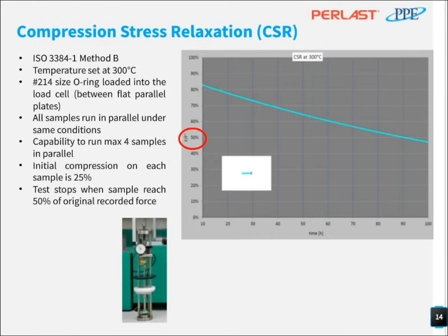And then it starts measuring the retention force, and then we put the whole system into the constant temperature oven, which is in this case 300 degrees C. We can use 4 cells at the same time in the oven, which gives us opportunity to test multiple materials at the same time.